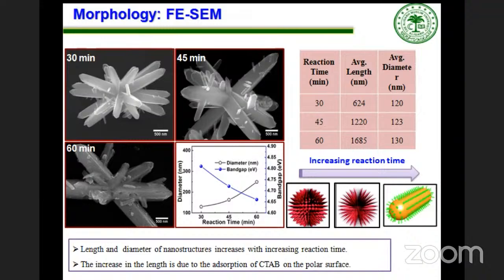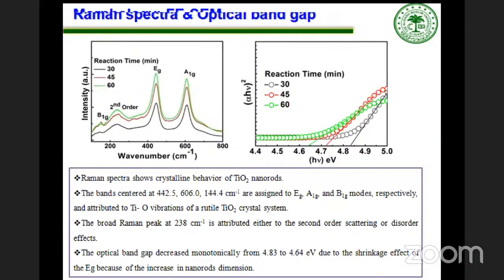And here in the table, we clearly see the increase in length of nanorods with increasing reaction time. This increase in length of nanorods is attributed to the adsorption of CTAB on the polar surfaces of titanium dioxide. To get more insight into the microstructure and crystalline behavior, we performed Raman spectroscopy of the as-prepared samples. It shows different Raman vibration bands of the titanium and oxygen bond, and all the bands are attributed to the pure rutile TiO2 crystal system. We also observed an extra broad band at 238 wave number, which is attributed to disorder effects.